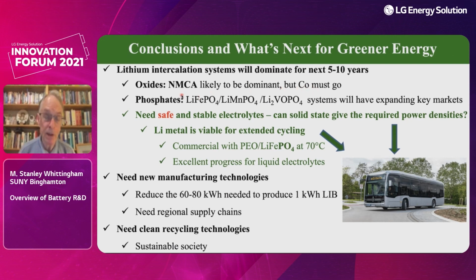I believe the phosphates are critical as we move forward. It's a means of getting rid of the cobalt and the nickel, and there's no rational reason in my mind why we're not using the olivines, these materials, more for grid energy storage rather than using the more expensive NMCs. And obviously these are less safe than these materials would be. And initially, grid storage, certainly in the US, we had a facility in Binghamton, used lithium iron phosphate. As I say, the next step is lithium manganese phosphate, and I expect some of these vanadium phosphates and others will take place in the market as well.